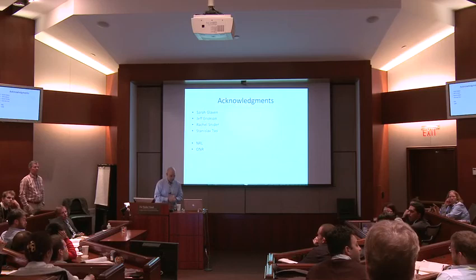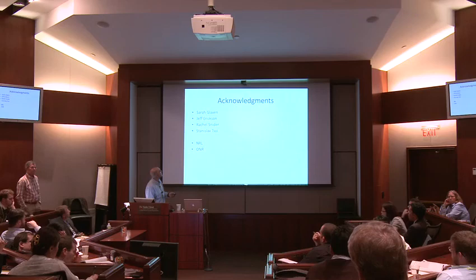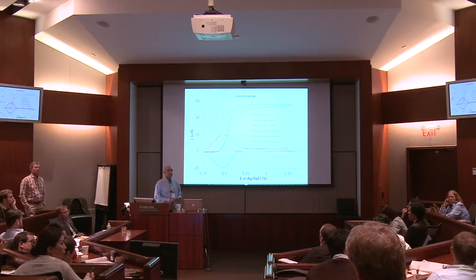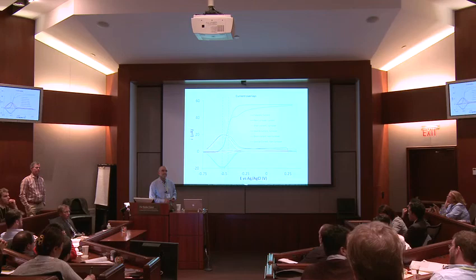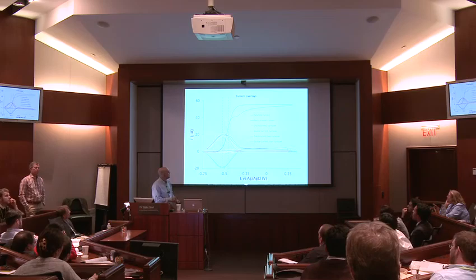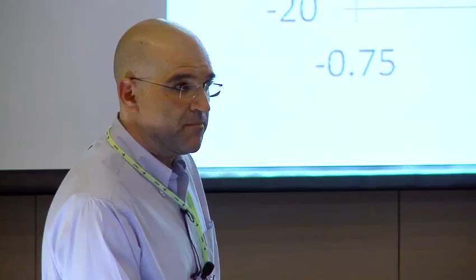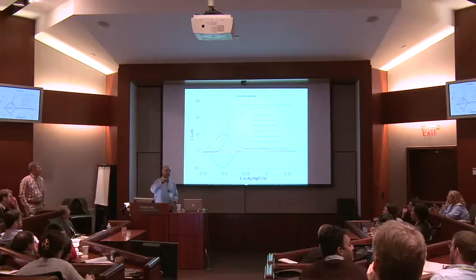So this data is all from 100 millivolts imposed potential across the gap? Yes. And if I understand it, at the higher potentials, you impose 100 millivolts, you don't see any current flowing across your gap. So if both electrodes are very positive in potential, so they're down here, they're both positive of the formal potential of the mediator, then there's no current. So what if you impose a slightly stronger potential, if you go to 200 millivolts?